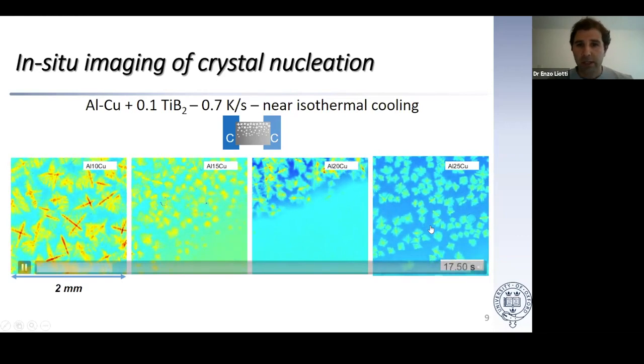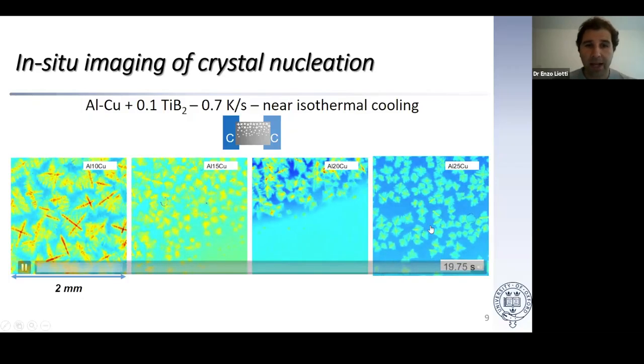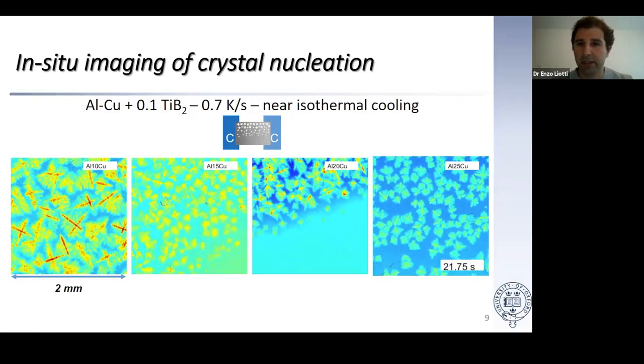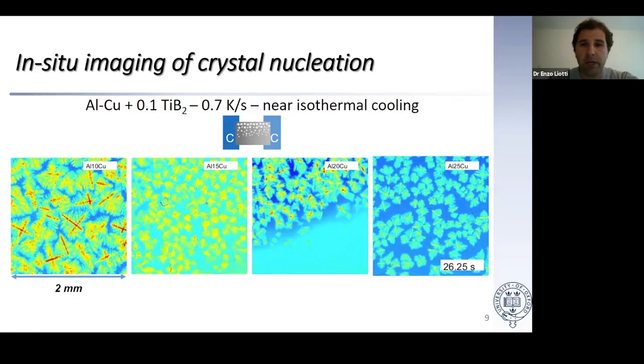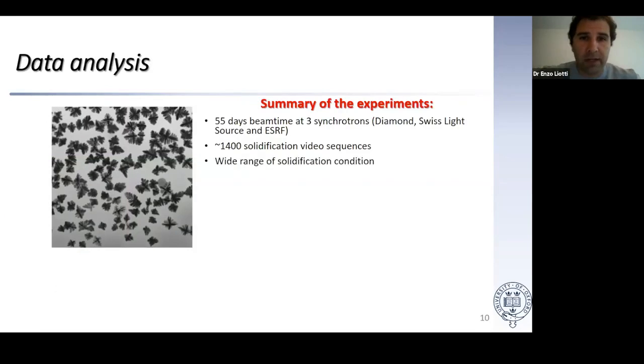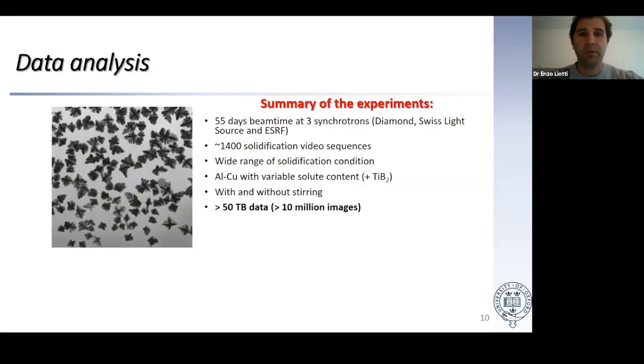Generally, there is a lot of detail that can be picked up by eye, and it is very important to understand the underlying mechanism of nucleation. However, the difficulty is how to extract this information. To give you an idea, over the years we've done on this specific experiment, more or less 55 days of beam time, during which we collected more than 1,400 video sequences, which account for about 50 terabytes or more than 10 million images. They cover a wide range of solidification conditions, different alloys, and even use a little electromagnetic stirrer to move and steer the liquid.